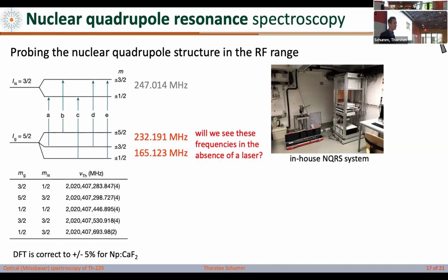One thing is, what can we do to check that? June already mentioned that these splittings down here are nicely in the radio frequency range, and probing these is the standard technique. In solid state physics, it's called nuclear quadrupole resonance spectroscopy. About a year ago, we started buying a nuclear quadrupole spectroscopy system, and we're trying to measure these in the ground state. In the first excited state, we can't yet because we don't have June's laser in our lab. This is one of my basement labs. But we can scan those. If we find those in RF spectroscopy, then we're sure the DFT is just wrong, and you shouldn't pay for the VASP code anymore. But if we find these frequencies in the ground state, everything's good.